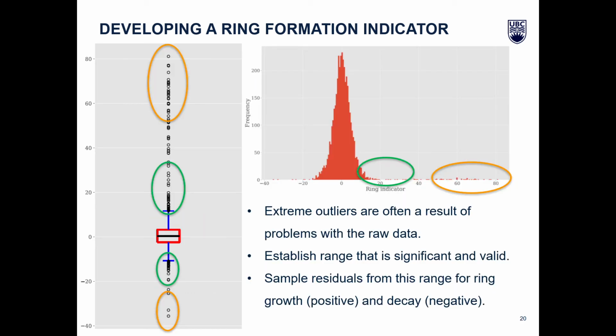Now that we have generated the residuals, we need to process them into a ring formation indicator. This slide shows two charts that represent the distribution of the temperature residuals in slightly different ways. On the left is a box and whisker plot, and on the right is a simple histogram. We are interested in residuals with large magnitudes, either positive or negative. The largest residual values are circled in orange, and they tend to correspond to problems with the raw data.